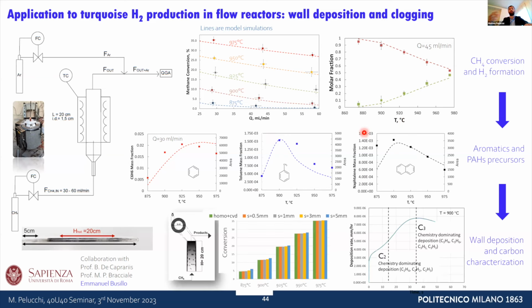We then started to look at the effect of deposition, different thicknesses of deposition on the reactor walls, on the conversion of methane. This is helpful to understand how and when you should stop the reactor from operation, do some cleaning, and restart again.